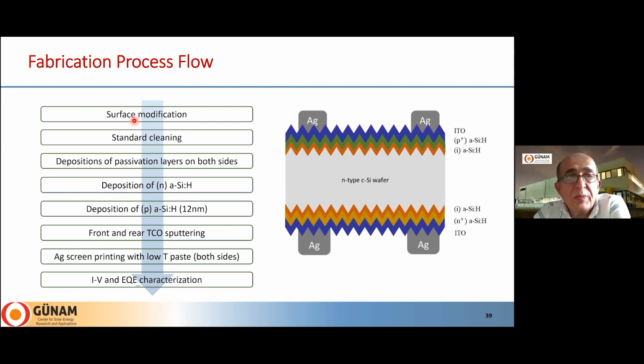After texturing, surface modification, and standard cleaning, the deposition of thin intrinsic amorphous silicon is done on both sides. The thickness is around 7 nanometers in our case. One side is coated with N-type amorphous silicon, the other side is coated with P-type amorphous silicon. On top of these amorphous layers, we deposit indium tin oxide or zinc oxide instead. And finally, we print silver fingers on both sides.